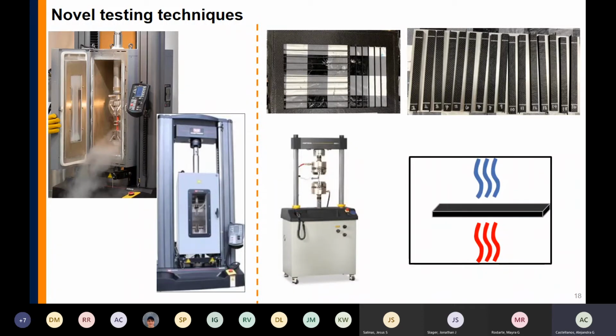Because again, remember that what has been done in the past is just exposing the whole composite to one environmental condition. A lot of researchers have reported that because this is not a realistic scenario, the failure mechanisms, what is going on inside your composite, will change when you have this thermal gradient effect. So we figured out a technique to keep this composite at two different temperatures while we're testing. I cannot disclose this because this is a project that is still going on, but we're working on publishing this work.